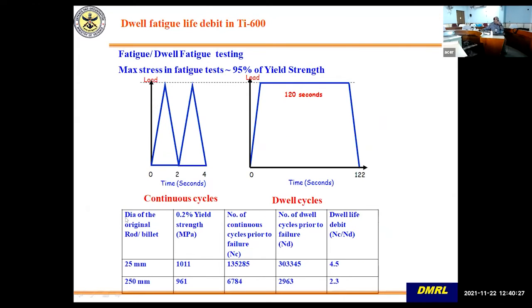When you test these materials for continuous fatigue, this is how a sawtooth fatigue looks like as compared to the dwell region. This is how a 120-second dwell around 95% of the yield strength looks. When you do that, this is the yield strength of both the materials. There is a slight difference because this is much finer material, so you get higher yield strength.